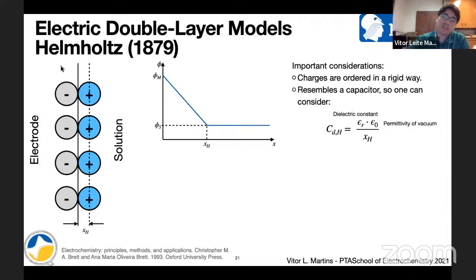And what did Helmholtz propose? He proposed that we have points of charge in the electrode. So the left here is the electrode and the right is the solution. So you have points of charge in the electrode, and you have points of charge in the solution to balance this electrode. And the important thing here is that this layer is rigid. So there is no movement of ions here. So it's balancing the charge and it's a rigid layer. It has a thickness. So the thickness goes through the middle or the center of the ions here. So this is the thickness of this layer in solution. All right. So remember that the layer in solution is much bigger than the layer in the electrode, and this is basically the thickness of the double layer.